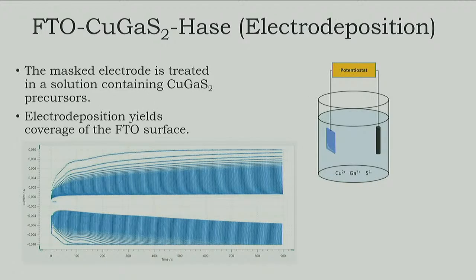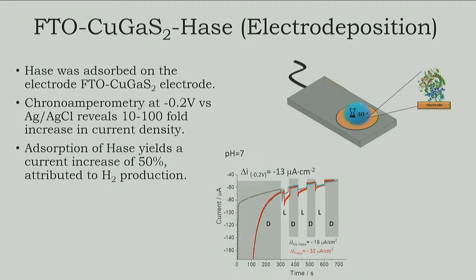So what else can we do, because this was not leading anywhere? In the end we found work on making electrodeposition of this. We just put the precursors here and made cycles of electrodeposition at different potentials, which is this process here. During 15 minutes the electrode was now giving a much better response. So this is ongoing research. I still don't have all the data to show, but we can see that we went from 1 microampere or less than 1 to 13 microamperes. So we are now working in this direction.